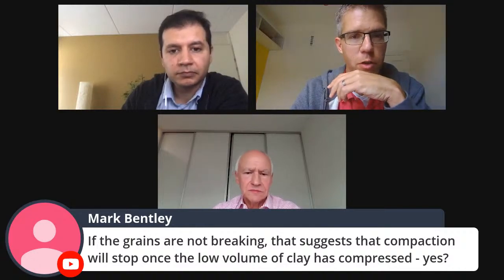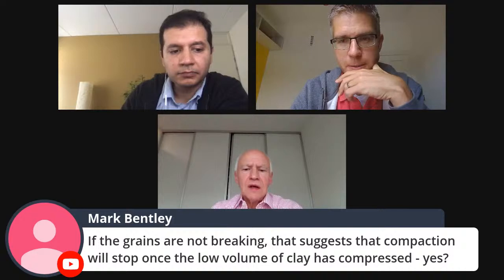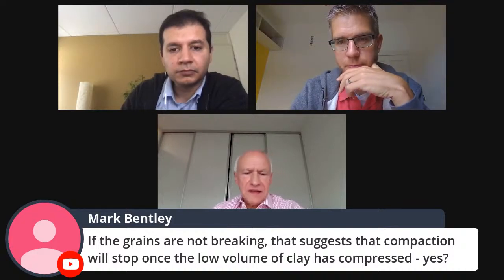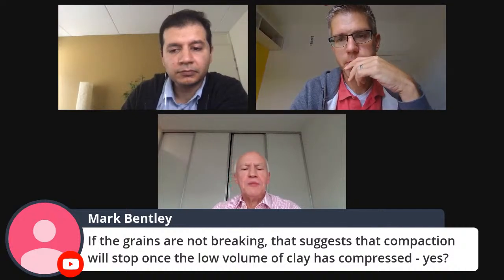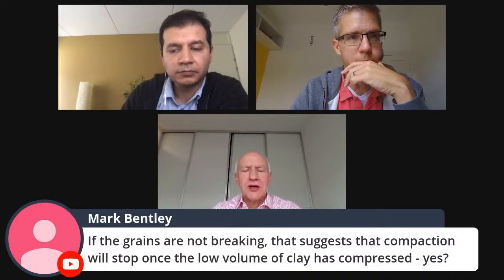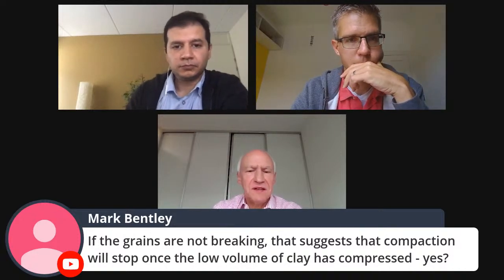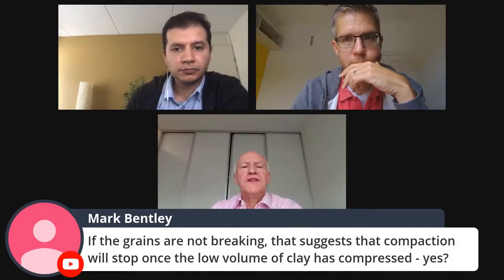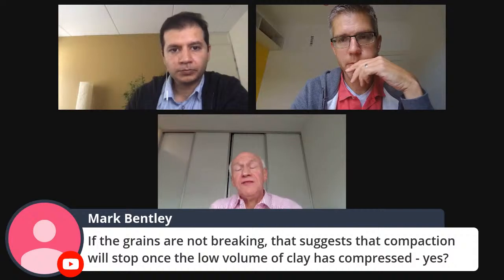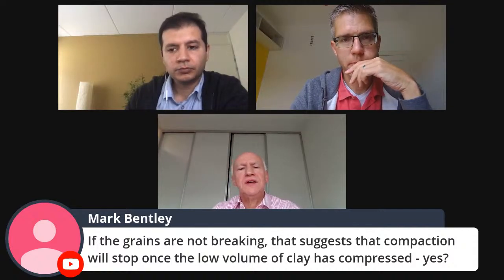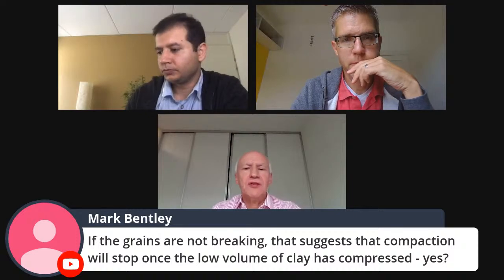Not breaking. That suggests that the compaction will stop once the low volume of clay has compressed. Is that correct? Yeah, basically what you see indeed is a transition between stages 2 and 3, from this linear behavior where compaction of the clay films dominates the inelastic behavior to the onset of microcracking. And that is in effect the onset of failure of the sample, and you get a macroscopic yield behavior of the sample and a load drop, and that correlates exactly with the onset of microcracking. And up until that point, the only thing that you see is this compression of these clay layers.